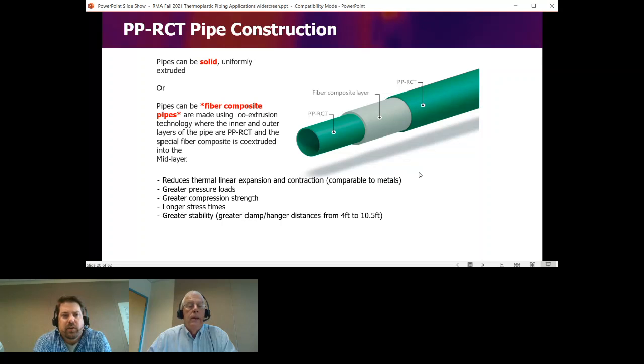PPRCT piping, for example, is one product offered by Aquatherm. Aquatherm is one of the more robust manufacturers who've captured a pretty big market share of the PPRCT market. The cool thing about the PPRCT is it's a composite pipe. What they do is they've impregnated a fiber composite layer between two standard layers of PPR piping. The benefit of that is it really curbs and mitigates the linear expansion. It's still not as good or as small as copper and steel, but it's manageable. That way we can start running higher and higher water temperatures in there, and you can control growth a little bit better.